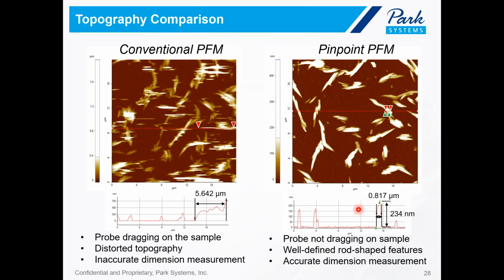From the topography images, the annealed phenanthrene polymer was resolved under both imaging conditions, and they were observed to be rod-shaped features with pointy ends, like the features right here. The height of the polymer rods was measured to range from tens to hundreds of nanometers, while the width was between several hundred nanometers and a couple of microns. It is noteworthy that the quality of the topography image obtained by PinPoint PFM is improved compared to that taken with the conventional PFM.